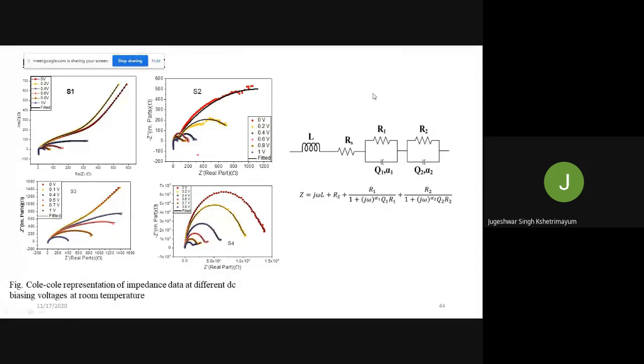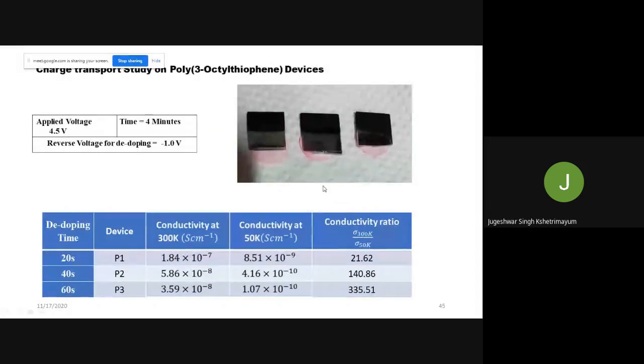All right, now this is the device. Whatever devices we prepared, all of them can be explained with this model. Then I apply my theory to another material, which we call octyl thiophene. Octyl thiophene is a little difficult to prepare as a film electrochemically, because the sticking property is very weak, so it cannot adhere to the material easily. So we use a special technique, and we are able to make octyl polymer devices on ITO glass. Okay, we are able to polymerize.